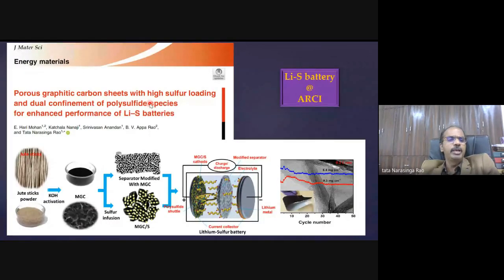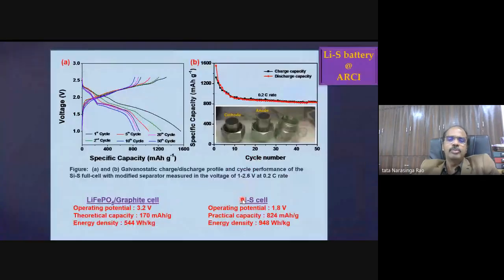You can see my team at ARCI. It is my student Harimohan, now in Germany, and recently we published this paper in Energy Materials. We make carbon from jute stick, nanoporous graphene-like carbon, and incorporate sulfur into the carbon, and then use this as the electrode. We also have the separator coated with this kind of carbon, so that any polysulfide gets trapped in the electrode, and a little bit coming out gets trapped on the carbon on the separator, so that it doesn't escape outside. That is what we have demonstrated here.